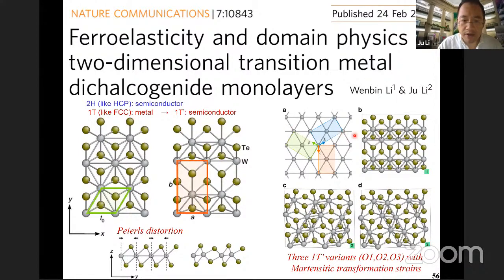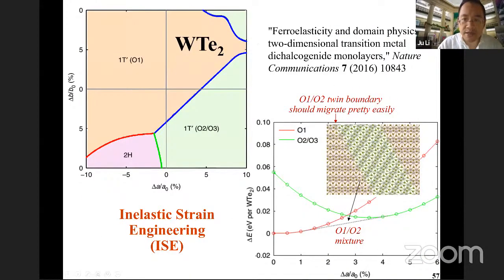And because you have one of these three reconstruction variants, there are actually three shear strain variants, and that would give rise to this martensitic transformation and the ferroelasticity. So we have predicted, for example, this T prime to another T prime variant twin boundary is very glissile. So when you strain it, it's going to have very mobile twin boundaries.